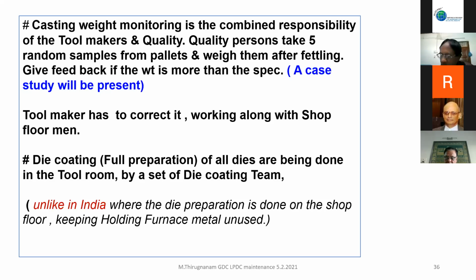Not more than that, not any more. If you coat beyond that, the die coat will not stick, it will peel off. After coating the rest, again for 1 hour, the die coat parts will be kept in a furnace at 400 degrees and then fully cured. These coatings are so strong, they will not peel off. Such is the way they work on it.